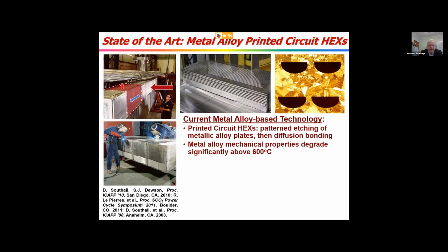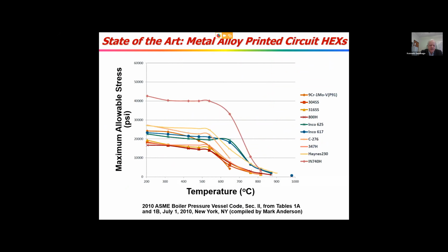But even beyond that, the challenge in doing this with metal alloys and using them at temperatures like 750, 800 C is the fact that the mechanical properties of the alloys start to degrade at these high temperatures. This is a plot obtained from the ASME boiler pressure vessel code. It was compiled by Mark Anderson at Wisconsin.